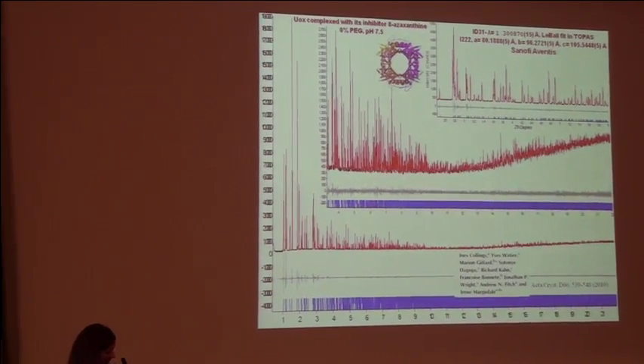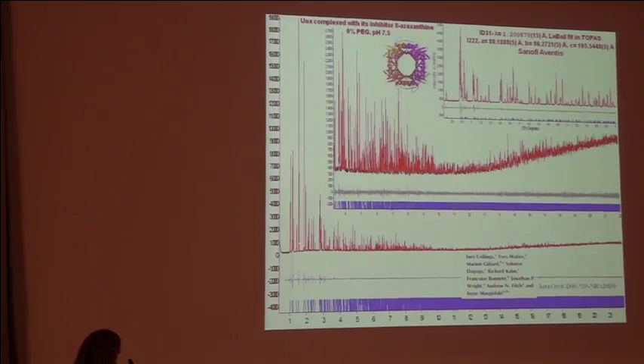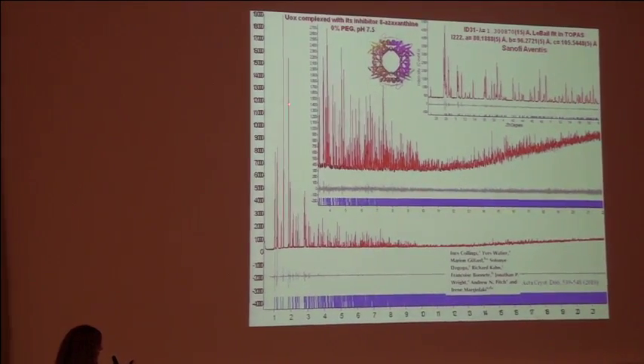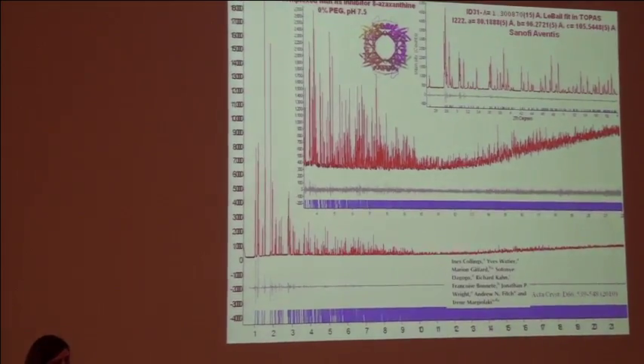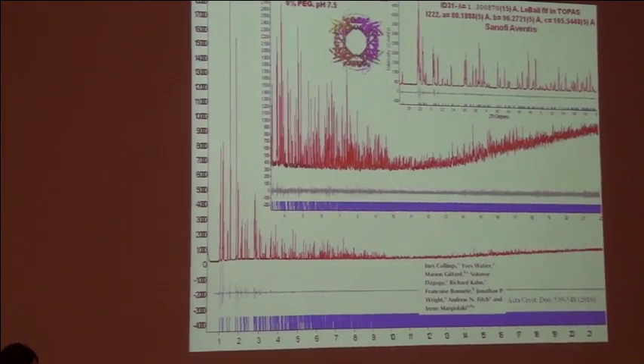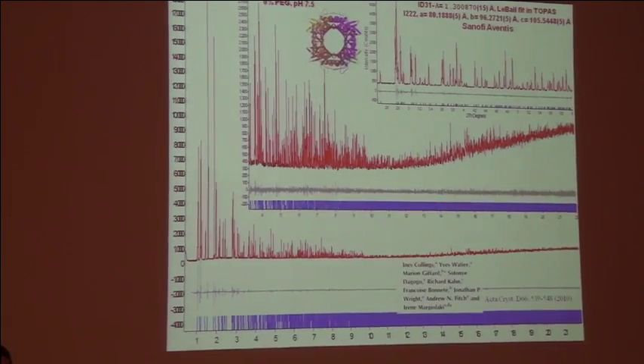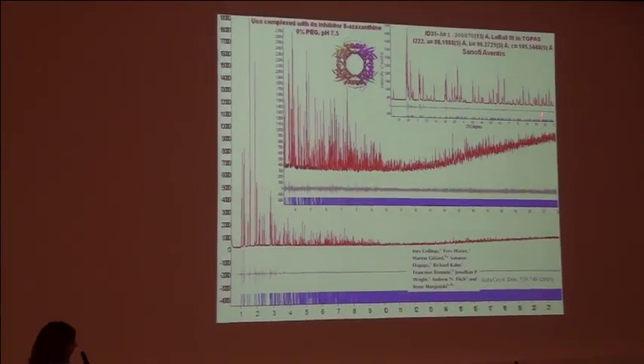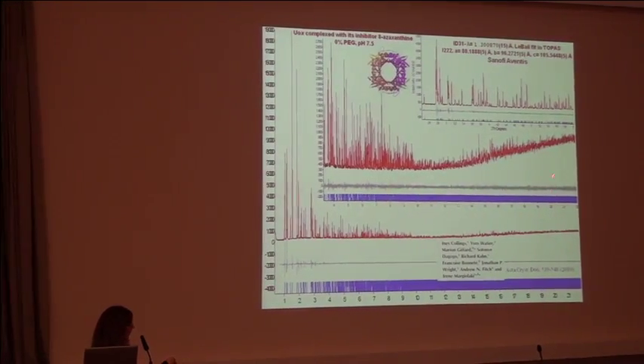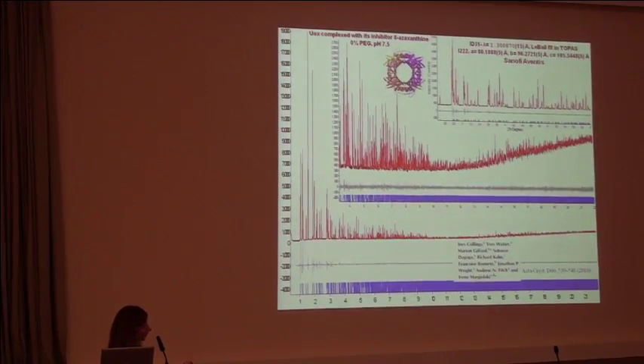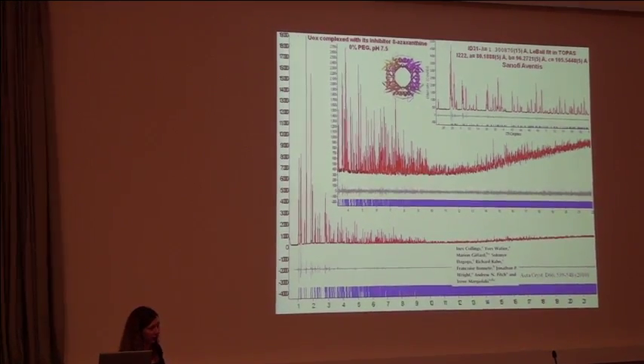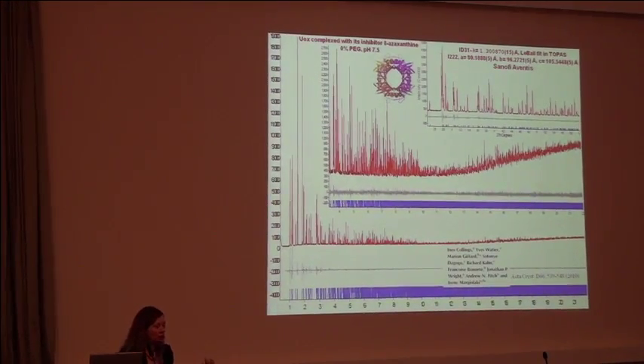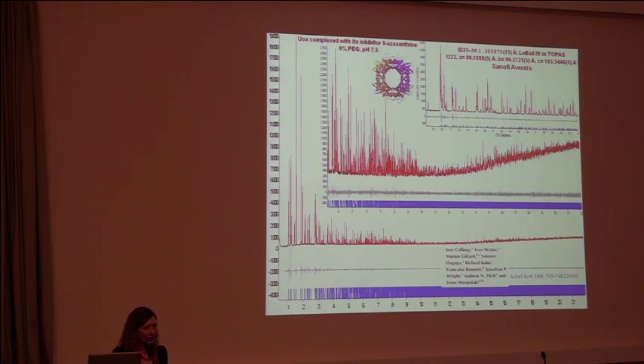High data quality means good signal to noise ratio, how well each peak is above the background, how narrow the diffraction lines are in order to be separated one from the other, and the maximum 2 theta at which we observe diffraction lines. Around here, to give you an idea, is 3 angstroms resolution in this spacing, and this is our most common data resolution we achieve. 3 angstroms, our best resolution has been 2.3, which is not too bad, thinking what you measure as your sample.